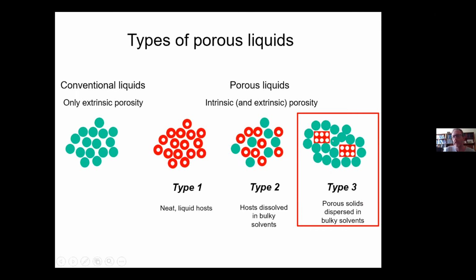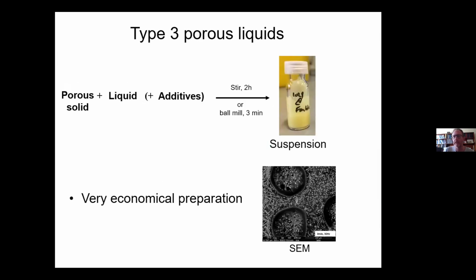As long as the liquid molecules, these green things here, as long as those are too big to fit into the pores in our particles, and as long as our particles stay dispersed, then effectively what we've got is a porous liquid. So it's now going to be a sort of milky thing. It's not going to be a clear solution, but it's hopefully going to have these interesting gas uptake properties. So these are what we call type 3 porous liquids, and it is in some cases very simple, porous solid plus a liquid. Bearing in mind, liquid has to be bulky, it can't fit inside. Sometimes with additives to help the stability of the dispersion, and you get these milky looking phases.